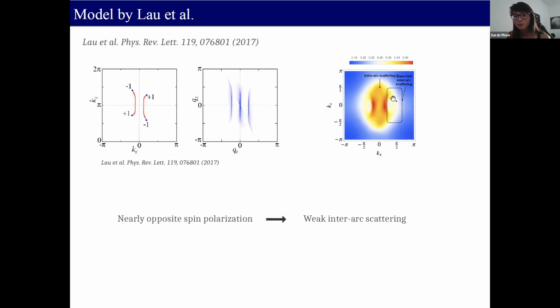So we see some weak shape here. And that's also something that is obtained in the JDOS by Lau et al., except that here, they don't set the color bar, but the intensity of the inter-arc shape is basically the same as the one for the intra-arc scattering.